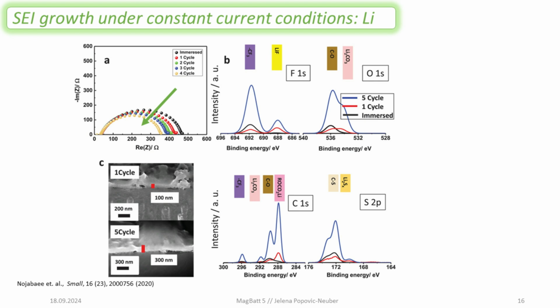We started looking at these materials when Mariam was doing her PhD. She sits here in the first row. So she tried looking into the changes of the resistances in symmetric lithium cells after cycling and has observed a very strange behavior, and that is that the resistance drops. But that was not something that we expected from what we have seen in the growth case.